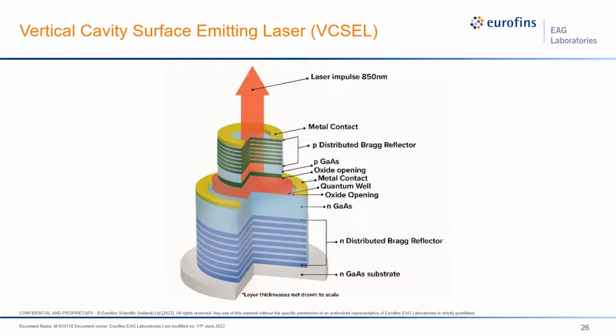Producing high-performance VCSELs requires optimization of various aspects of the device, including the aluminum composition and gradient between high and low refractive index mirror layers, the dopant profile between the mirror layers, the composition of the aperture layer, assuming it's an oxide-confined VCSEL, the active layer impurity content, the aluminum grading on either side of the active layer, and of course the thickness of all the layers within the structure. An example of a P-core SIMS depth profile of a complete VCSEL is shown in the next slide.